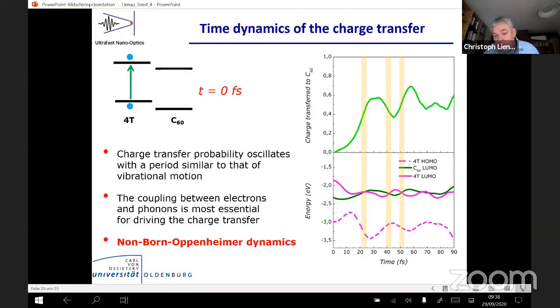This would induce phase shifts or so, but it's important that the electron-phonon coupling in the system is so strong that it dominates over basically disorder-induced effects on the level splitting. So you don't need to get the level ordering absolutely right. There's a certain tolerance, because again, electron-phonon coupling is so strong. Okay. Thank you.